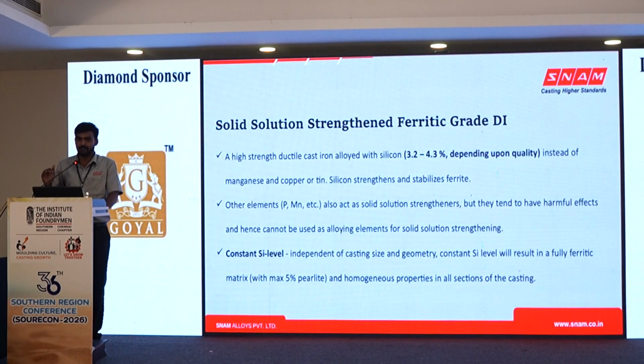As the silicon percentage increases, the mechanical properties increase, and also at constant silicon level, we can achieve a fully ferritic matrix throughout the casting section thickness, independent of casting size or geometry. But other elements like phosphorus and manganese we cannot use because they can have a harmful effect in ferritic grade ductile iron.